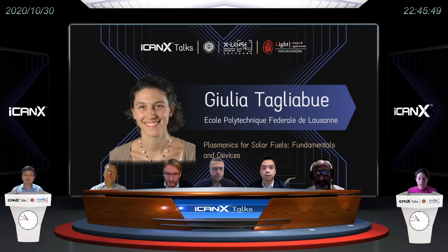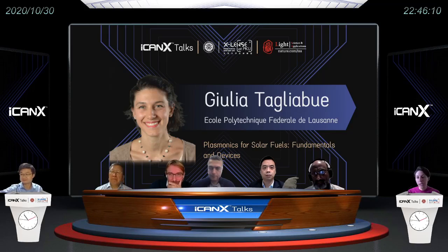Yes, thank you. Very good question. I want to remark that in my experiments, I wasn't after the performance of the device, because my focus was on the perfect control of all of the properties at the interface and the structure and the shape, so that we could very easily compare with the theory through numerical calculation and ab initio calculations. That said, we know that the low internal and external quantum efficiency we obtained were primarily dictated by the low injection probability at the metal semiconductor interface.